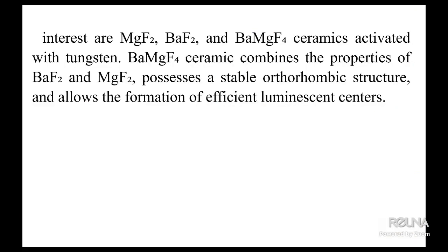In our work, we synthesize ceramic materials based on metal fluorides. Conventional high-temperature synthesis of fluoride ceramics is accompanied by losses of activators due to the formation of volatile compounds and the deterioration of material properties. Radiation synthesis makes it possible to overcome this limitation by enabling activator incorporation without additional additives and by producing homogeneous radiation-resistant ceramics. We are interested in MgF2, BaF2, and BaMgF4 ceramics activated with tungsten.